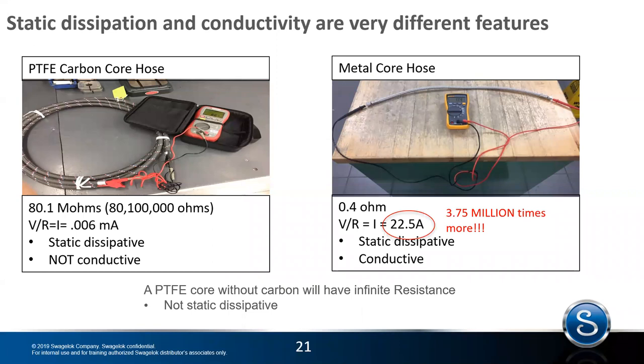22.5 amps of current is flowing through this hose. And the hose on the left is a Teflon core hose with a non-metal braid, and what is flowing through it is 0.006 milliamps of current. This is nearly 4 million times less. So we consider this hose on the left to be non-conductive. There are situations where a hose should be non-conductive. The hose should not allow ground from one connection to the other connection electrically. It needs to be electrically isolated. This hose on the left, although it will dissipate static, does have some current flow, but it is not considered conductive. It still has a very, very high resistance to conductive flow.